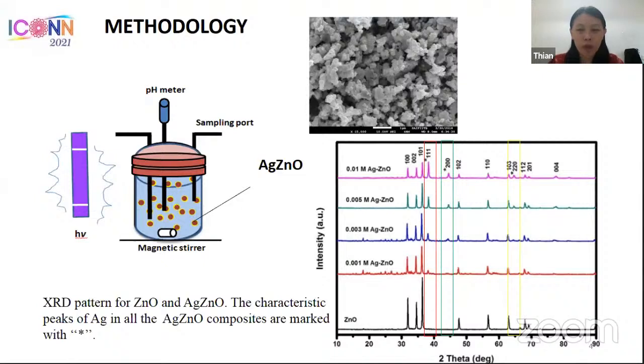And so this is our experimental setup. As you can see here on the left side of my screen, this is the reactor, and then on the side there is this portable handheld UV lamp, and then there is this silver zinc oxide, the FEG SEM image, which shows the presence of the zinc oxide, and then we have the XRD graph. If you can see here, there are colored boxes, which again affirm the presence of silver in our nanocomposite.